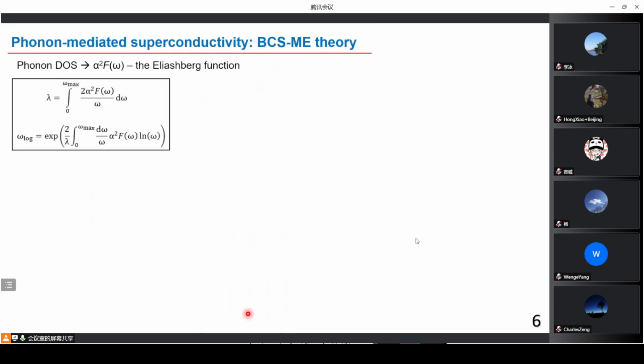Hydrides can be described by a relatively simple theory. It's phonon-mediated superconductivity, a commonly used theory, the so-called Bardeen-Cooper-Schrieffer-Migdal-Eliashberg theory, where we have only one important function for us. It's the Eliashberg function, which describes superconductivity in polyhydrides. And actually, not the whole function is important, but only two main parameters. It's the electron-phonon coupling coefficient, lambda, so-called, and the characteristic phonon frequency, characteristic phonon energy, which is called logarithmic